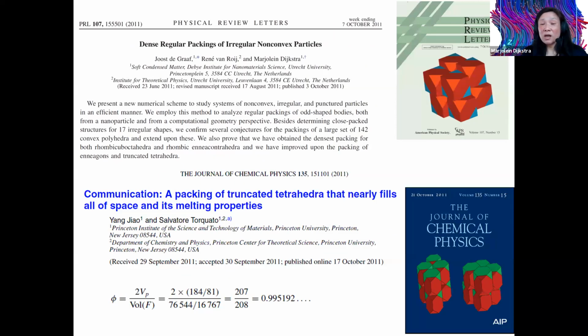We also looked, for instance, at truncated tetrahedra. They can nearly fill all of space. This was demonstrated by Chen, Engel and Glotzer, who showed that the densest packing of these truncated tetrahedra is 207 over 208. So almost 99.5192% of space is filled by these truncated tetrahedra. These truncated tetrahedra form a dimer. I will come back later on to these dimer lattices again. These dimers are centrosymmetric compounds, and these centrosymmetric compounds will just self-assemble onto a Bravais lattice.